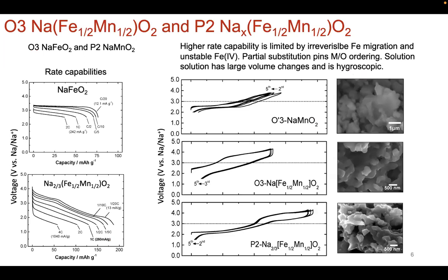So, ultimately what you want to know is how do these materials behave electrochemically? When you start to desodiate and also then resodiate, how does this affect rate capabilities, and also how does it affect capacity? Well, from here, you see that if you have the end members like sodium manganese oxide, sodium iron oxide, the rate capabilities for the solid solutions are actually better. These materials are able to achieve higher capacity at higher C rates.